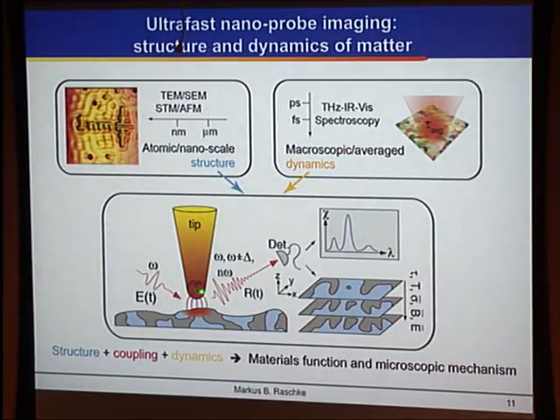And if we now interact the tip with the sample, say through atomic force interaction as a tool to control this distance, then we retain all degrees of freedom which are non-interacting with the optical frequencies to still control sample properties. Whether it is a change in temperature, we can apply strain, and unlike in STM, we can apply magnetic fields or electric fields and drive a system through quantum phases.